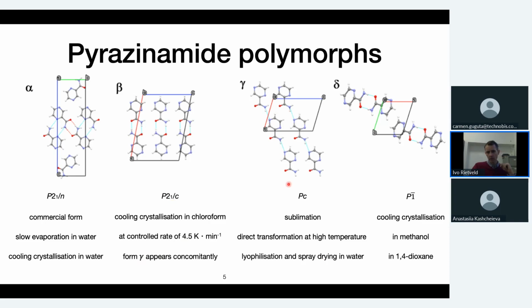Gamma itself can be obtained. It's the high temperature form of the system. You can get it by sublimation at high temperature, or it doesn't matter which form you take. You heat it up in the DSC or you heat it up in the oven, and at a certain temperature, it will always transform into the gamma form. So that can be done. For the rest, you can also get it by spray drying and lyophilization. So obviously, it is the form that crystallizes out rather rapidly if the system is, say, not so very stable, it seems.